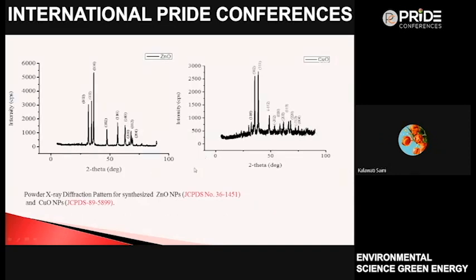These are the powder XRD. Herein, the crystallinity of the zinc oxide particle is higher than the copper oxide, which is synthesized in the same manner, but crystallinity is higher for the zinc oxide particle. And these are the JCPDS numbers: for zinc oxide 36-1451, and for copper oxide the JCPDS number is 89-5899.